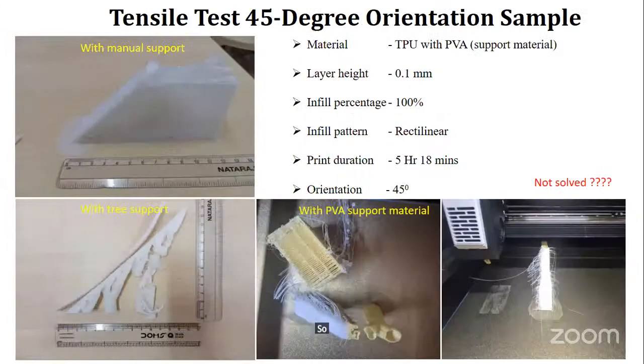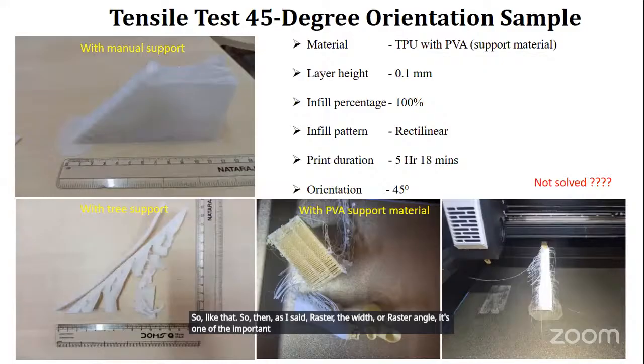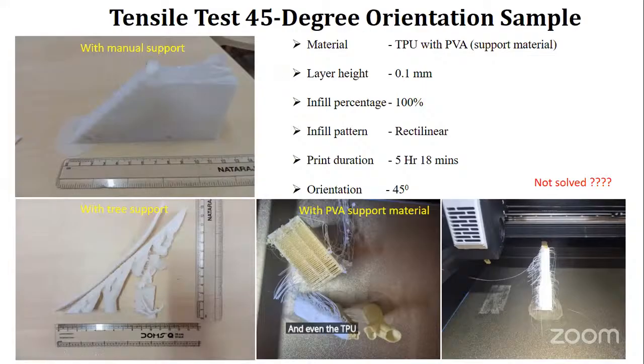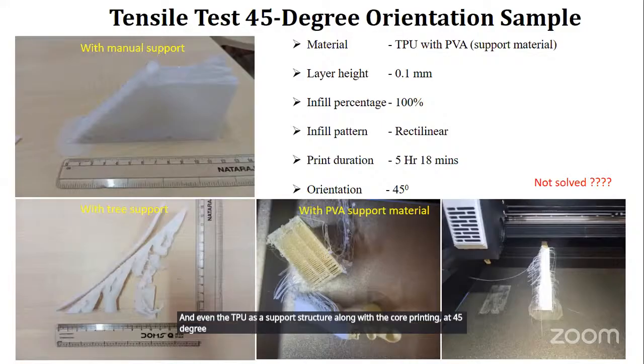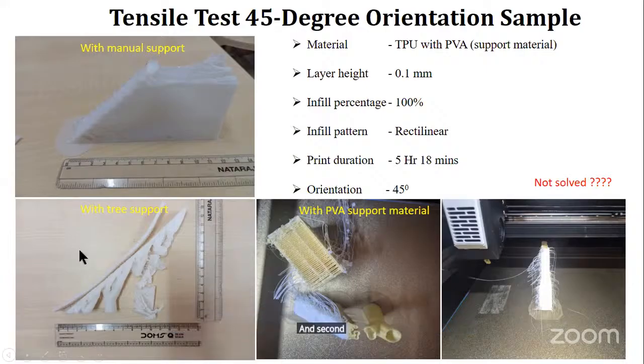So as I said, raster width or raster angle is one of the important process parameters in FDM technology. Then we tried printing this TPU with a support structure of PVA, and even TPU as a support structure along with the core printing at 45 degree. We printed successfully at 0 degree, we printed successfully at 90 degree, but at 45 degree we were unable to print it. You can see the first one is the manual support that we gave, and the second is the tree support. In the slicing software, you have different supports.